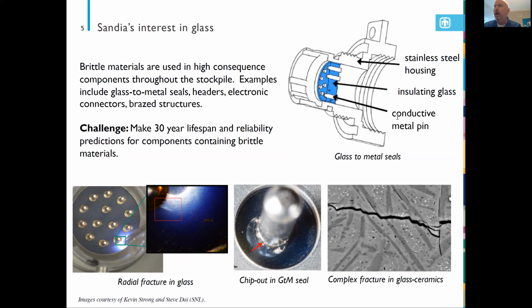Now the glass, which is highlighted in blue there, actually has two intentions. First off, it serves as an electrical standoff between the electrical pins. And the second is it's actually a hermetic seal. One of the things that they're interested in is making sure that the environment at the head of the electrical connector does not interact with the environment at the tail of the electrical connector. And as such, one of the design requirements for this glass to metal seal is that they have to have that glass in compression. With very specific coefficients of thermal expansion of the glass relative to the pin and relative to the metal housing, they can assure that the glass will be in a compression state, enforcing this hermetic seal.